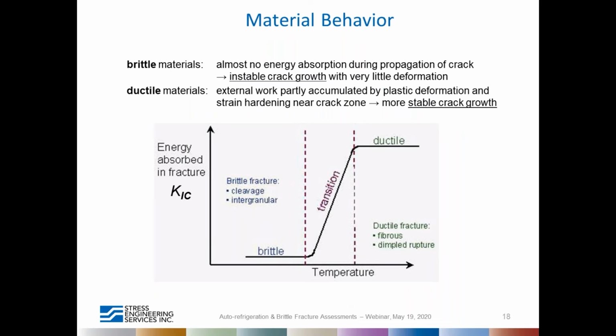So the same material can behave in a ductile manner at a higher temperature and can behave in a brittle manner at a lower temperature. So this is a curve they call the toughness versus ductility transition curve. And this particular location on this curve is referred to as the nil ductility temperature location. So this plot is between what's called the fracture toughness, which is a measure of absorbed energy in fracture, versus the temperature. So as you can see, a material can go to a brittle phase if the temperature goes lower.